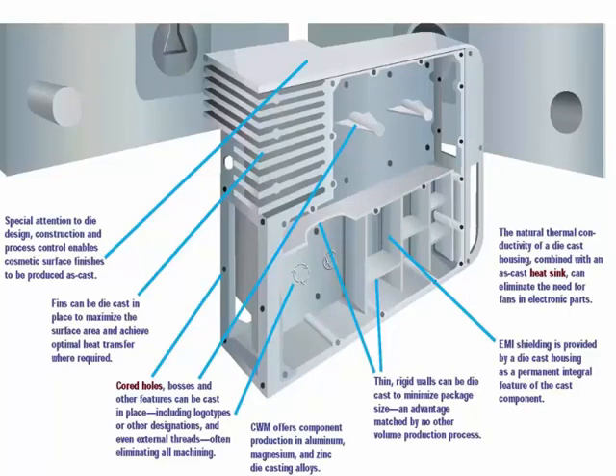Here's a blow-up of the part that is created by this die, this fictitious die. And you can see some of the features that we've already talked about that can be incorporated into a part. This part has fins on this end, so it's utilized as a heat sink. In some cases, people utilize fins on a die casting instead of having to do a separate component with fins for a heat sink application. You can see some of the very thin walls that are achieved on this part. All of these exterior holes that you see, we attempt to get those as cast, depending on the size and functionality. We'll try our best to get them as cast instead of having to go in as a separate secondary operation.